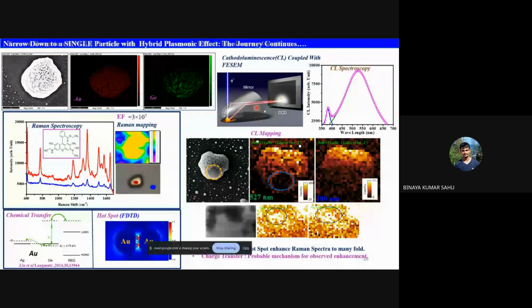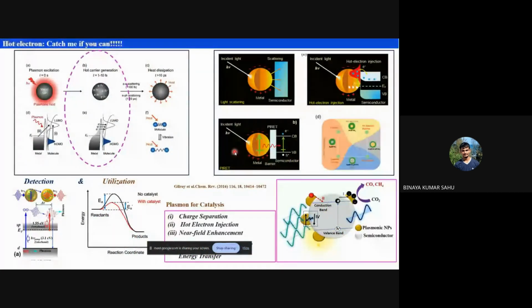Okay, and again we did some CL, cathodoluminescence imaging, and again we continued doing SERS. Okay, because still we can see this narrowed down to a single particle hybrid plasmonic effect. This is a single particle. Of course it's of micron size. But here we saw this plasmonic activity, theoretically as well as experimentally using cathodoluminescence.